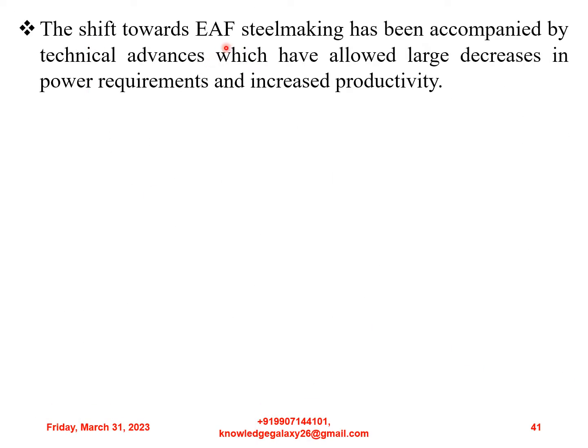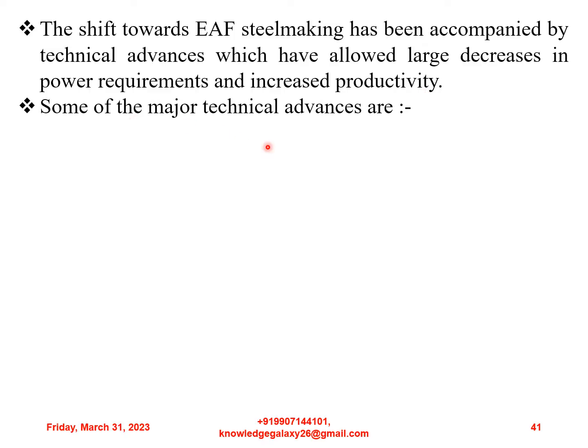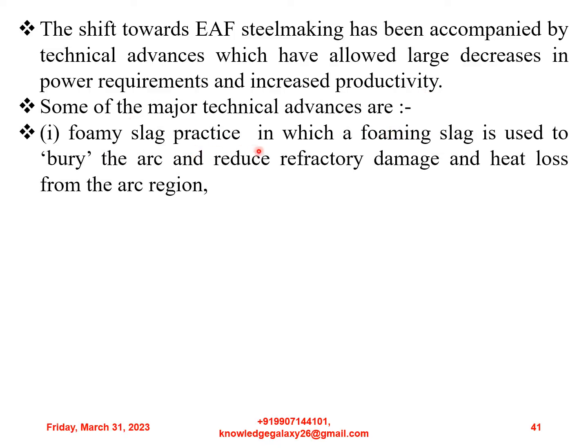The shift towards electric arc furnace steel making has been accompanied by technical advances which have allowed large decreases in power requirements and increased productivity. Some of the major technical advances are: first, foaming slag practice, in which a foaming slag is used to bury the arc and reduce refractory damage and heat loss from the arc region.